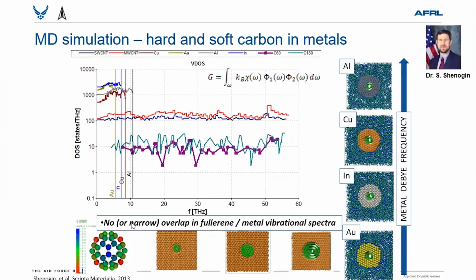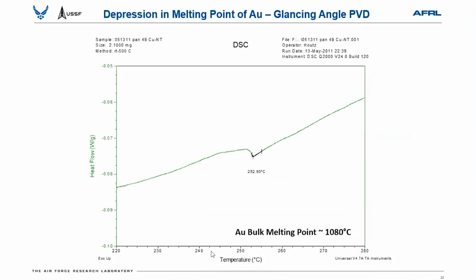So you can pick different metals: gold, copper, aluminum, and so forth. We demonstrated that with gold. Gold's melting point is over 1,000 degrees, whereas carbon disintegrates after 550 degrees Celsius. So how do you tackle this issue? But there's a brighter side. If you make it nano size, in this case 5 or 4 nanometer, we see the melting temperature of gold drops to 260.